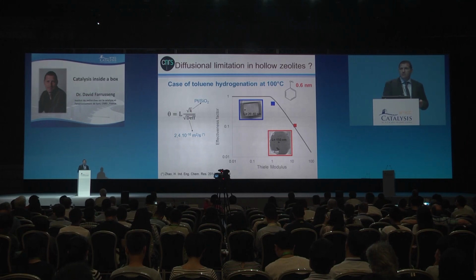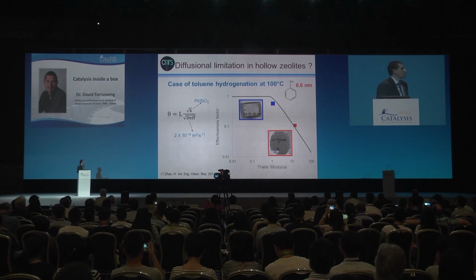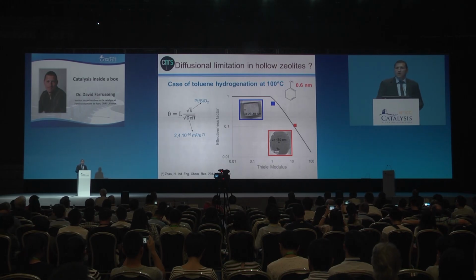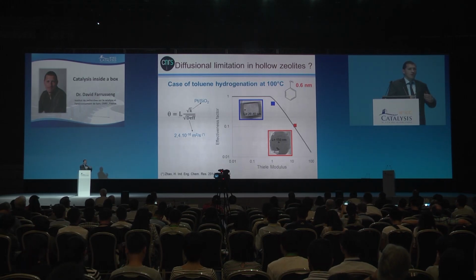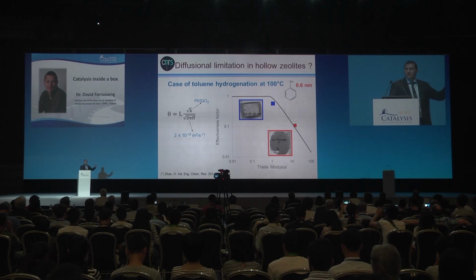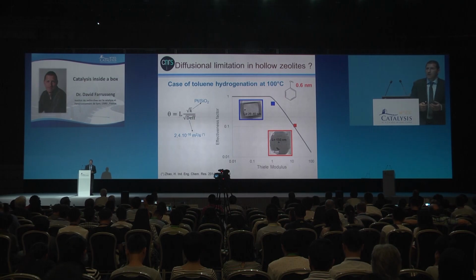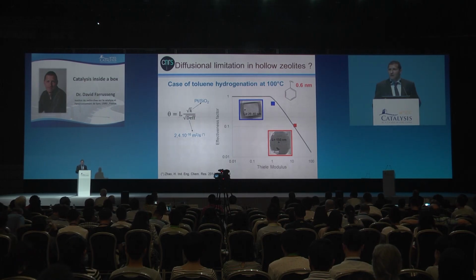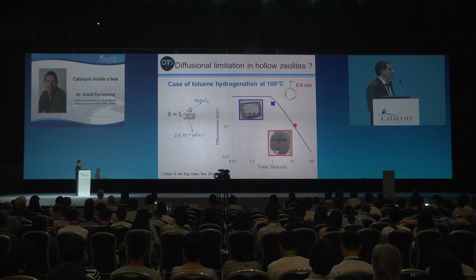It has a very slow diffusion rate, while the hydrogenation is a fast reaction. So we are here in the case where we have a fast reaction and a slow diffusion. It's a perfect case to be limited by the diffusion. And how can you estimate that? Well, it's by the estimation of the Thiele modulus that is put here.